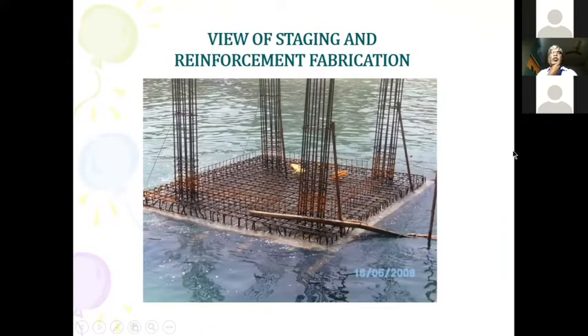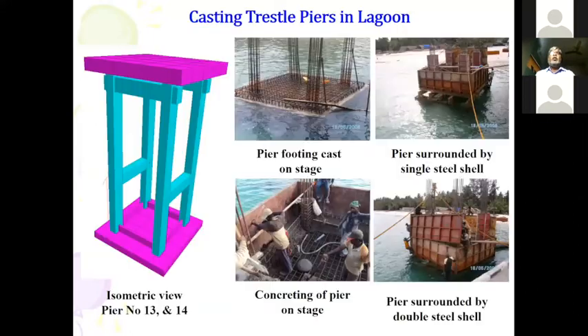Especially in the wave breaking zone, it was not a single isolated footing, and partial of this has been done, and this was also floated. Now the problem is, at least the sump, you'll be able to bring it through the mouth of the island. Where it comes to the open sea, the buoyancy is not an issue at all. But in this case, the depth is going to be very low. So you need to provide additional buoyancy effort.